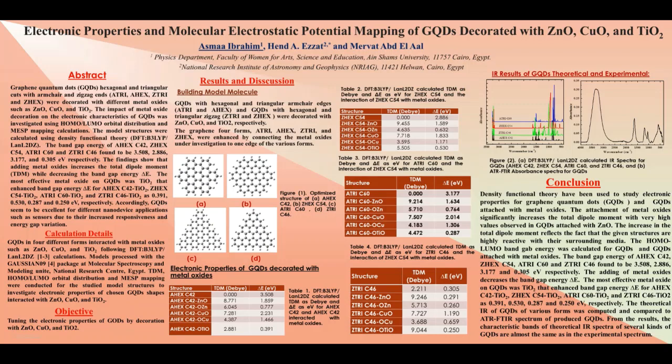Conclusion: density functional theory has been used to study electronic properties of graphene quantum dots and graphene quantum dots attached with metal oxide. The attachment of metal oxide significantly increased the total dipole moment, with a very high value observed in graphene quantum dots attached with zinc oxide. The increase in total dipole moment reflects the fact that the given structures are highly reactive with their surrounding media.